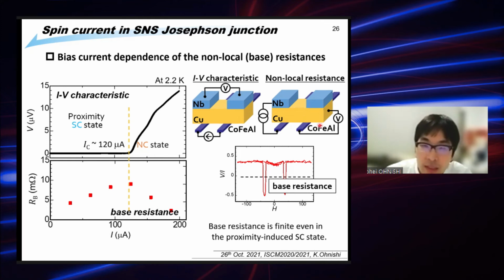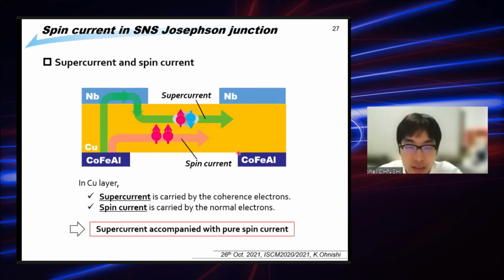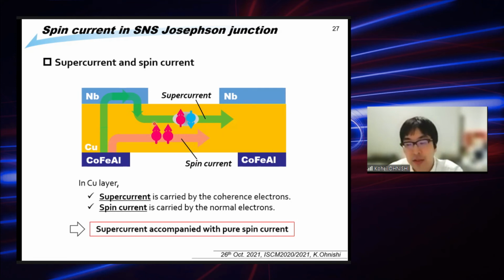So by this result, we can consider that in this structure, in the copper layer, the supercurrent is carried by the coherent electrons, while the spin current is carried by the normal electrons. Obviously this spin current is carried by the normal electrons, but this is a pure spin current, so the voltage drop induced by this pure spin current is cancelled at this junction. So we cannot measure any voltage drop between the superconducting niobium two parts. So in this copper layer, we can see the supercurrent accompanied with the pure spin current.